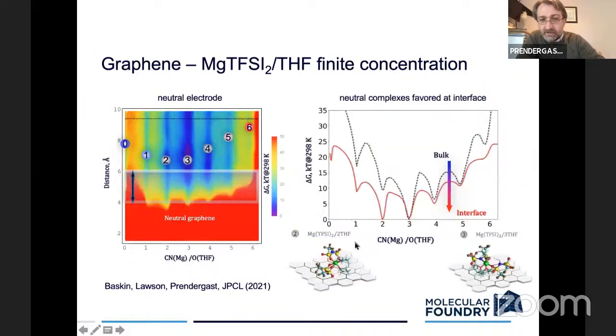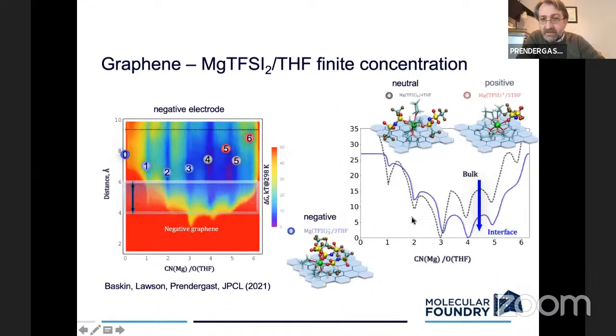If I go back and forth here, coordination numbers 2 and 3 were stable without the bias. And now with a charge on the interface, we go to maybe 4 and possibly some of 3-fold coordination. And it's amazing, you would expect the charged objects to be drawn more closely to the negative electrodes, so the positively charged objects. But actually the dominant species of this interface are neutral and maybe sometimes even negative, in addition to positive species that involve contact ion pairs.